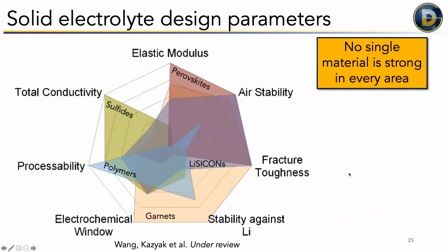You have the sulfide materials here, which have very good conductivity, which means that the lithium ions can move back and forth very well, but they're not stable in air and they're not stable against lithium metal, which is a problem, but it's easy to process them. In contrast, you have these garnets, which are an oxide material. They are stable against lithium. They have a wide electrochemical stability window. They're air stable, but the conductivity isn't quite as high and they're not processable. So the game really becomes, well, which of these doesn't have an Achilles heel that can't be overcome?